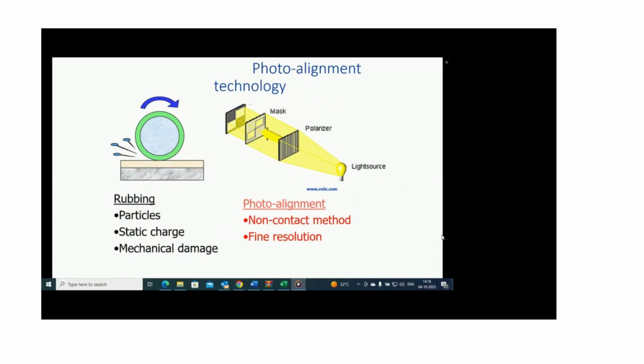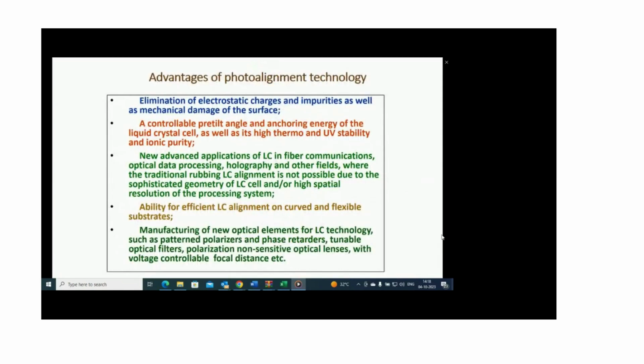Rubbing means that you make particles, static charge, and mechanical damage. So in principle, you should use photoalignment technology, which is a non-contact method with fine resolution. So you don't touch, and then you eliminate electrostatic charges and impurities. You have a controllable tilt angle and anchoring energy. And in principle, you can have new advanced applications, fiber communications, and curved and flexible substrates, where usual liquid crystal technology is very difficult to apply.